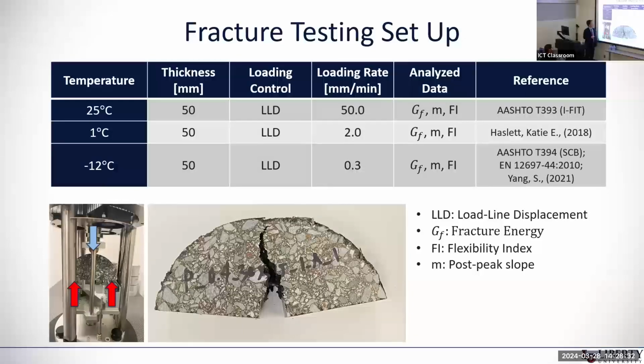Same for the 1 degree Celsius, and then we try to keep the same thickness of the specimen to minimize the geometry dependency of the fracture energy. And also we apply the 2 millimeter per minute of the loading rate, and then we look at all the same, the fracture energy and the flexibility index.